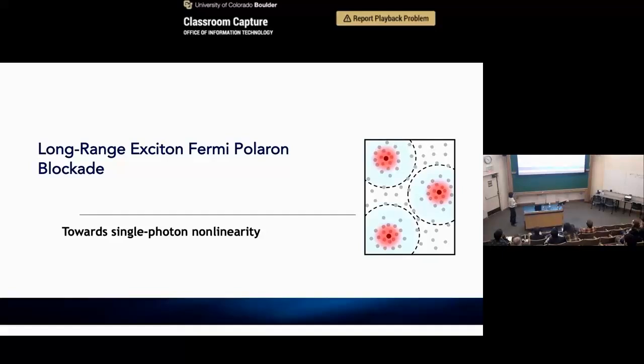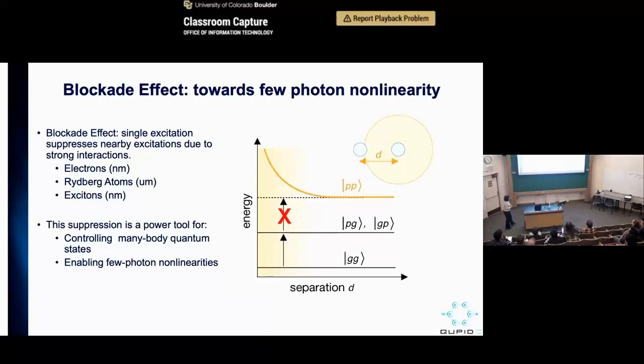One last thing, also about increasing interaction between excitons. In this case, we look at a much simpler system, which is a single layer. The reason we are interested in this is, can we increase the interaction length scale of excitons? These excitons are mostly composite bosons, coming from electrons and holes. If you think about over what length scale they interact, it is only on the order of nanometers, 10 nanometers at most, from the dipolar interaction that I mentioned before.